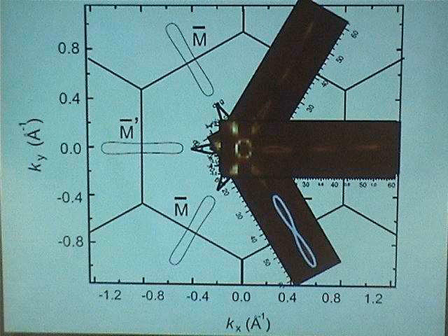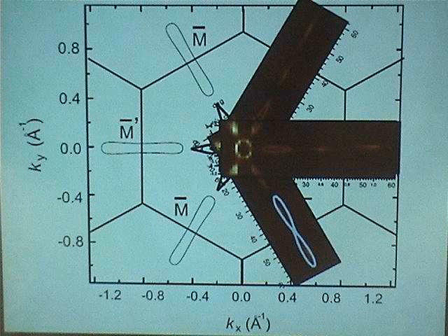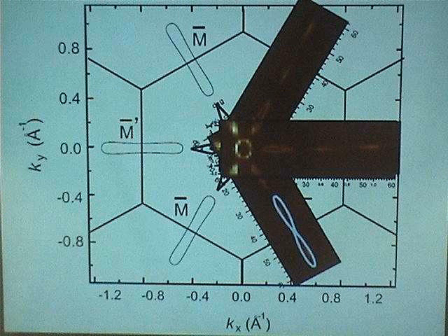And now that we have a detailed map of the three-dimensional band structure, I can use that internal detail to fine align the Fermi surface with the Brillouin zone, because our experimental precision alignment is not that great as we would love. And this is often not done in high-Tc or other compounds, because there people don't really go through those details.